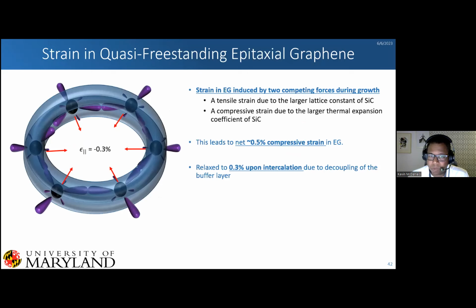Okay, and so a little bit further explanation of the strain effect. When we grow graphene, we have two competing strain effects: the tensile strain due to the larger lattice constant of silicon carbide, and then a compressive strain due to the larger thermal expansion coefficient of silicon carbide. So this leads to a net compressive strain of 0.5%. And then when we intercalate it, it relaxes to around 0.3% because of this decoupling of our buffer layer.